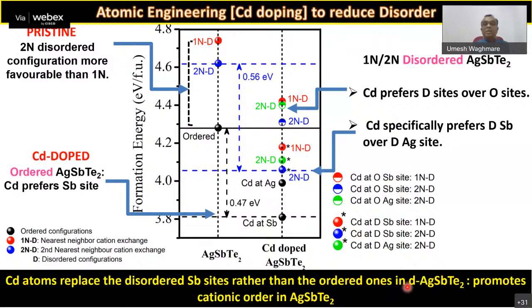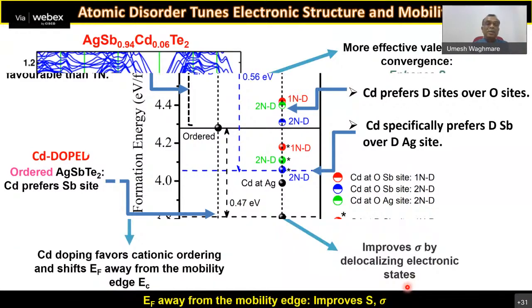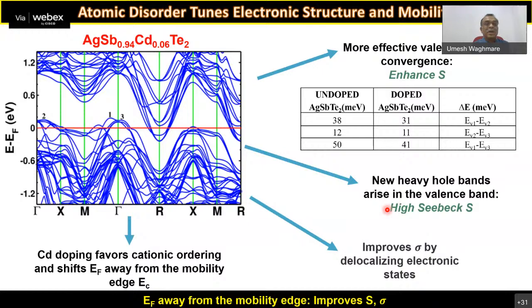So this is where experiment was used and showed, of course, these are all calculations with cadmium doping, we could eliminate those defect states and get a beautiful semiconductor. Not only that, we could get many more bands at the conduction and valence edges, and that is called band convergence, which enhances the Seebeck coefficient, and also enhances the electrical conductivity by delocalizing the electrons associated with it.